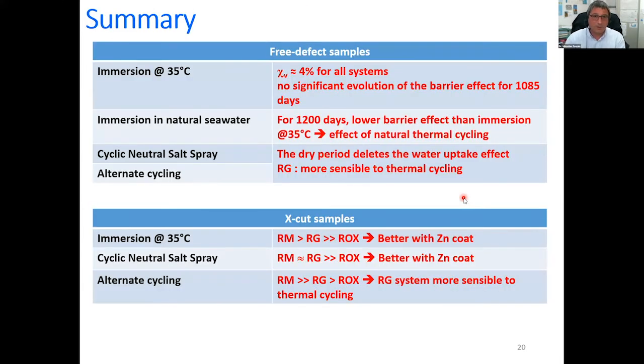So this is a summary of the results. Just to remind you that with the immersion at 35 degrees C, we've got a water uptake value of about 4% for all the systems, but no significant evolution of the barrier effect for more than 1,000 days of immersion. For the immersion in natural seawater, for more than 1,000 days, we had a lower barrier effect than immersion at 35 degrees C. Maybe this is the effect of the natural thermal cycling. And for cyclic neutral salt spray and alternate cycling, we had the same observations. The dry period delays the water uptake effect, and the RG system seems to be more sensitive to thermal cycling.